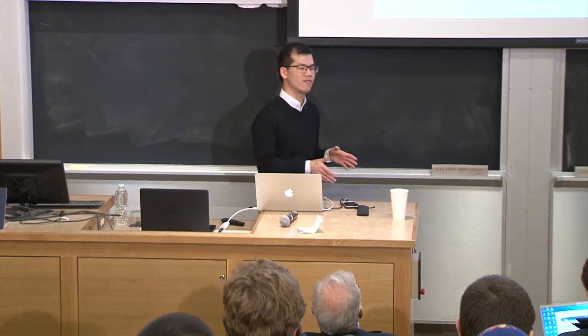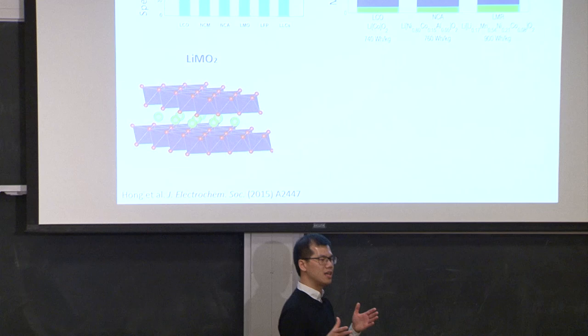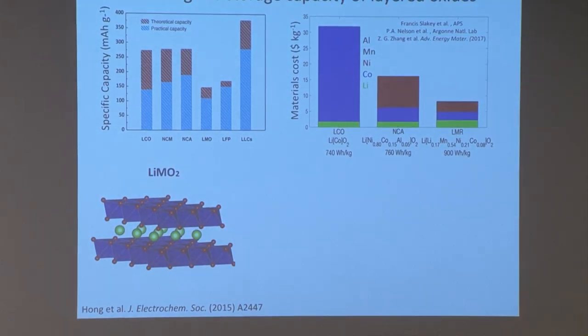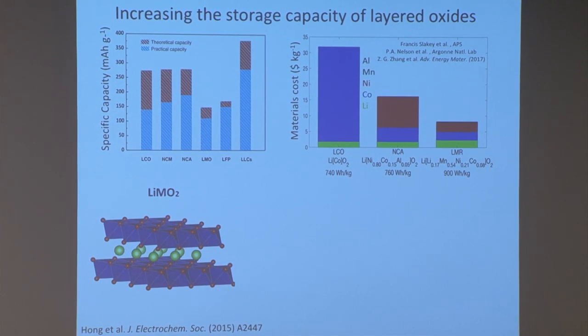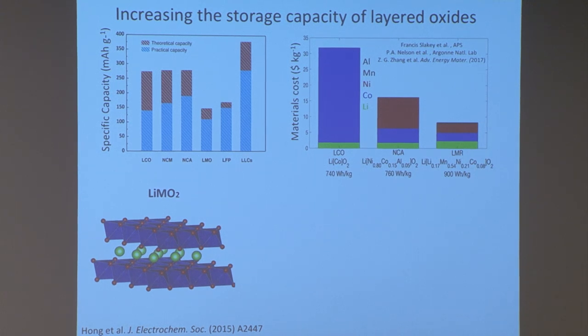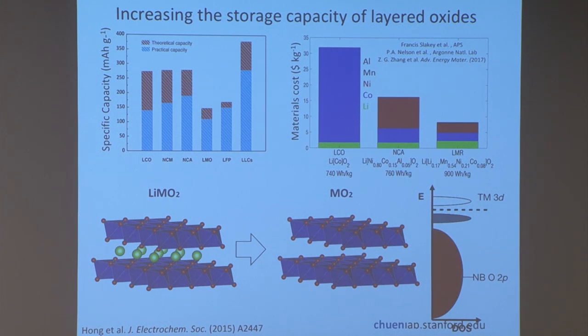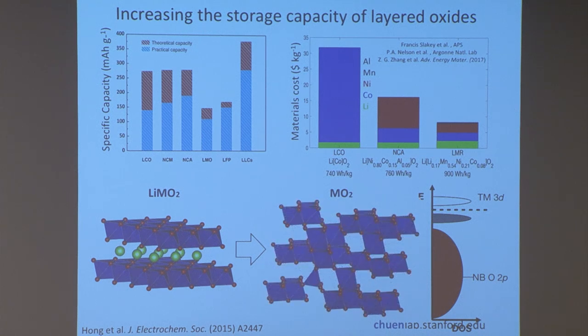So one of the key components of a lithium-ion battery, one of the reservoirs of lithium, is typically a metal oxide. So this stores the low-energy reservoir of lithium, typically some form of layered materials, as shown here. Layered materials are very good because the transport of lithium, which is in green here, can go fairly unimpeded. So if you maintain this layer structure, the transport property is excellent. But the problem is, after you use the material, it begins to disorder. Okay, so rather than maintaining this perfect structure, you have the metal ions and the lithium ions moving around. So what happens, you lose the perfect layer structure, and that causes your storage capacity to decrease. Furthermore, because you are inserting and removing lithium, you're also reducing and oxidizing the material.